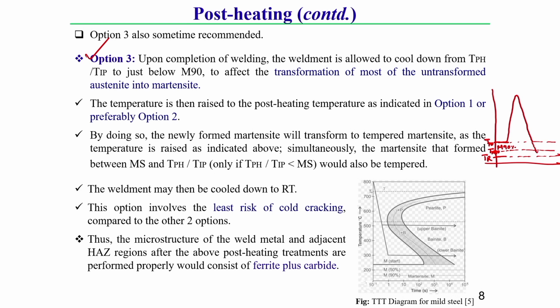After that, we heat the welded specimen to a temperature, where either we can follow option 1, which means going up only to the preheating temperature, or we can go to around 600 to 750 degree centigrade depending on the type of steel. This is generally below recrystallization temperature; keep this in mind. Then we hold that temperature for a particular time, and after that we cool down the welded specimen to room temperature gradually. This is called option 3.